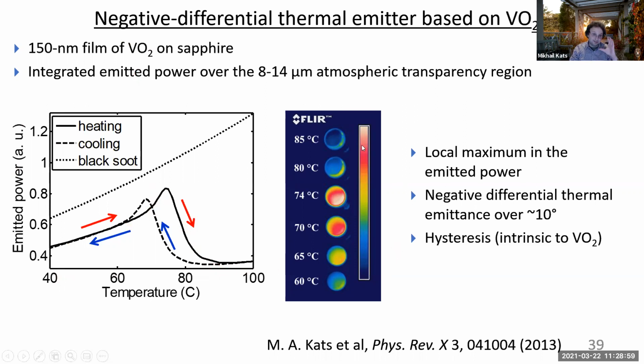And so if you look at the samples with an infrared camera, so this is 6 snapshots taken with an infrared camera, you can see that at 75 degrees Celsius, the object looks like it's a lot hotter than it looks when it's at 85 degrees Celsius. So this is very, very strange, but the reason this happens is because essentially the emissivity of this VO2 and sapphire drops dramatically as a function of temperature as you encounter the phase transition, because the optical properties change so much. And so then you have this dramatic effect. And we thought that was quite interesting.